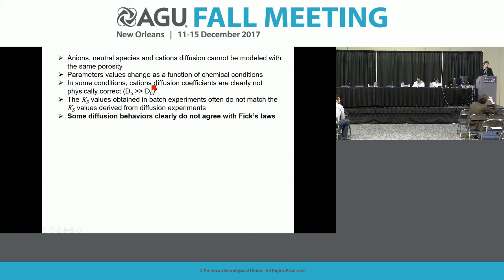In some conditions, we have parameters that are completely unphysical. For example, your pore diffusion coefficient is far larger than the self-diffusion coefficient of the cations of interest in water. And also the retention parameters, named KD here, that you can obtain from batch experiments do not match with the KD values derived from the diffusion experiments. And sometimes what has been observed is that some diffusion behaviors clearly do not agree with Fick's law.